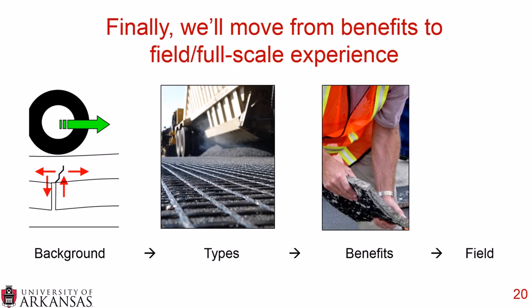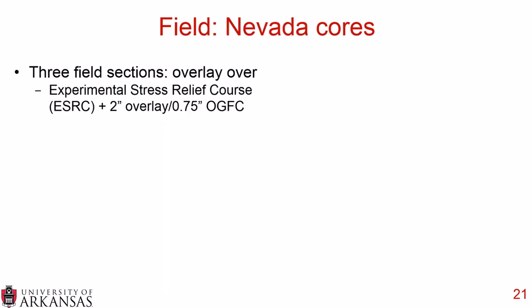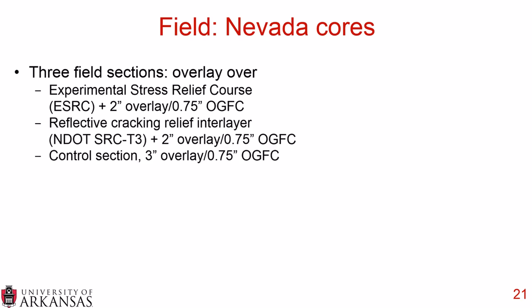Now, finally, we're going to move from the benefits to some field and full-scale experiments that I was able to find. Let's start with Nevada. In the state of Nevada, they looked at 3 field sections, and they placed an overlay over an experimental stress relief course, or ESRC. Then they placed a 2-inch overlay and a 3/4-inch open graded friction course, or OGFC. They also placed the traditional Nevada reflective crack relief interlayer, which is Nevada DOT SRC-T3, plus the overlay and OGFC. And then they did a control section, which was simply a 3-inch overlay and a 3/4-inch OGFC.